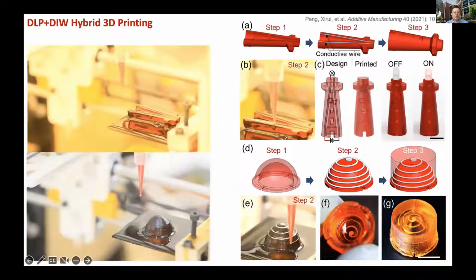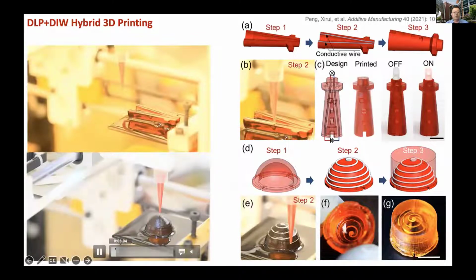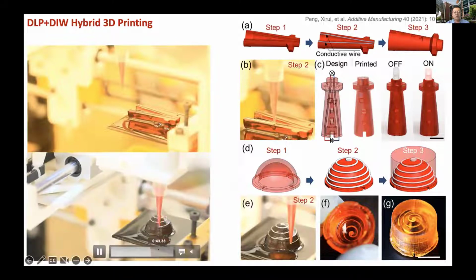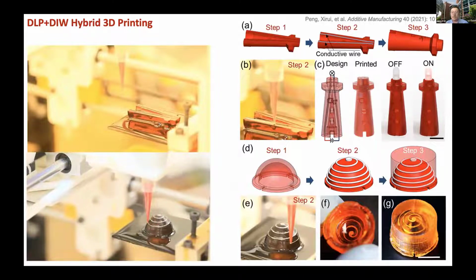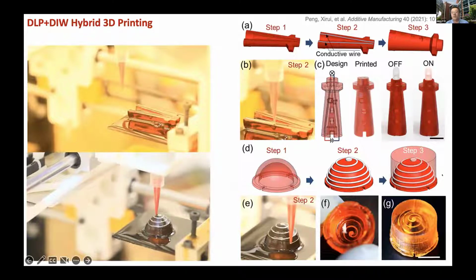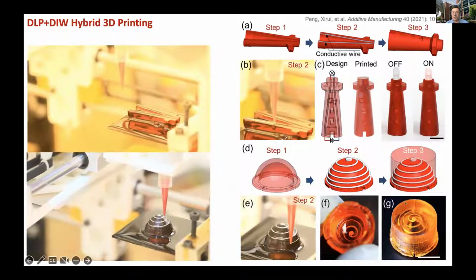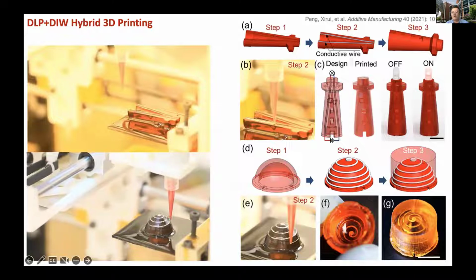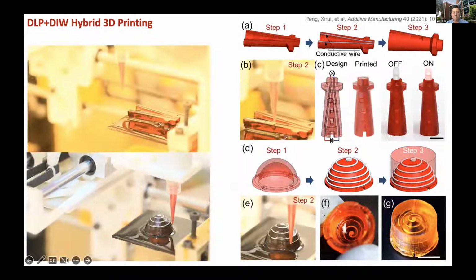We can also design our code. We can actually print on a conical surface. This actually, we rewrite the G code, so we can actually print the structures. You can see it's continuous, just a helical line in the space. And then after printing, we can finish up another printing of the DLP, so we can cover this kind of helical conductive trace in these kinds of structures.